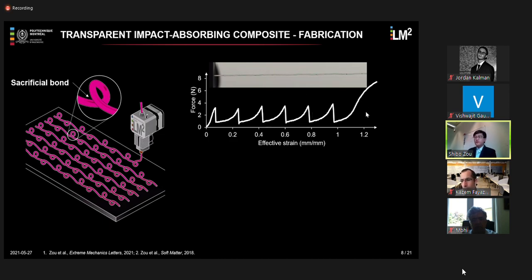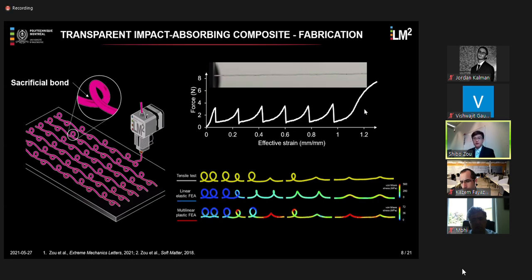And we also developed finite elements simulation of this kind of structure. And we found that during the unfolding process of the fiber, large-scale plastic deformation was happening along the fiber, and this explains why basically all the energy dissipation comes from the plastic deformation of the unfolding fiber.